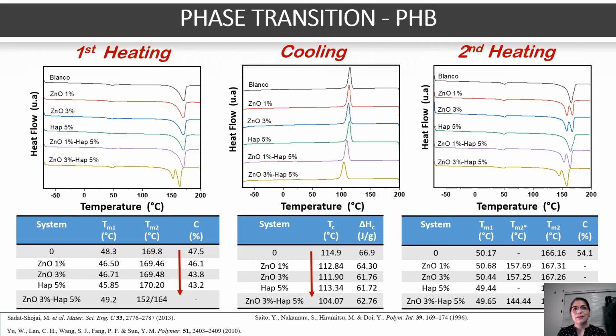The delay in the polymer crystallization process is possibly caused by interference in the packing of the polymer chains. In the second heating process, two melting transitions appear and a decrease in the melting temperature of the crystalline phases, with a more pronounced effect in the ternary system formulated with 3% of zinc oxide, possibly due to the presence of agglomeration.